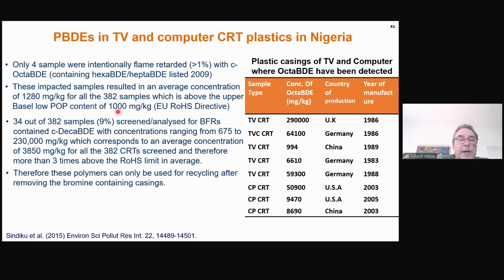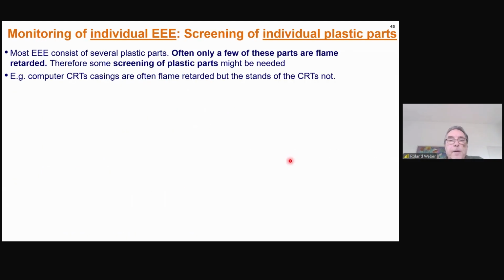And 34 of the 382 samples, around 9%, contain deca-BDE in concentration between 675 to 230,000 milligram per kilogram. Also here, the average concentration would be nearly 4,000 milligram. This means 3 to 4 times above the low POP limit of the Stockholm Convention. Therefore, if you just mix these samples together, these polymers can only be used for recycling after removal of bromine containing cases and separation.